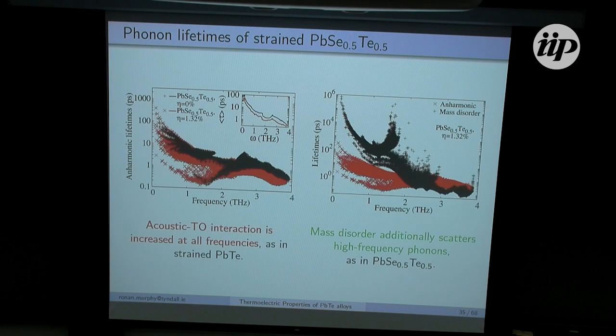And now to look at the phonon lifetimes. So I have here the anharmonic phonon lifetimes. Again, black is unstrained and red is strained. And again, you see the same story developing, where we see a substantial reduction in the phonon lifetimes due to that strain. And again, we see this reduction in phonon lifetimes is maintained across the frequency spectrum.